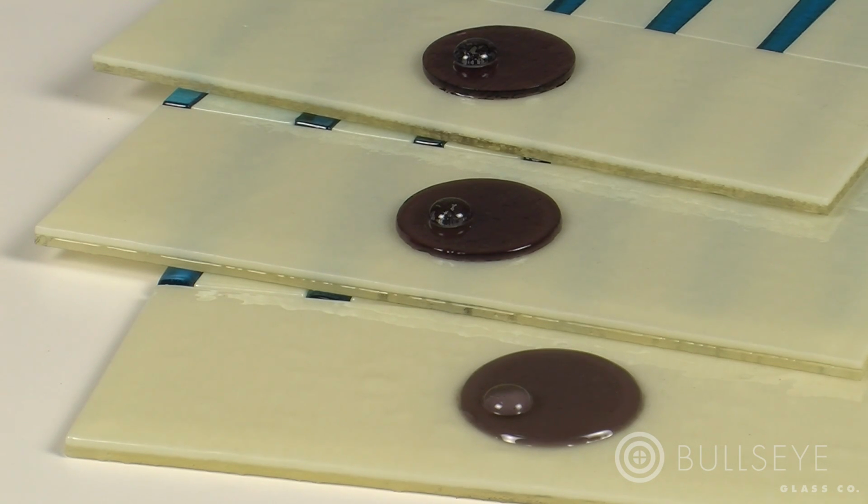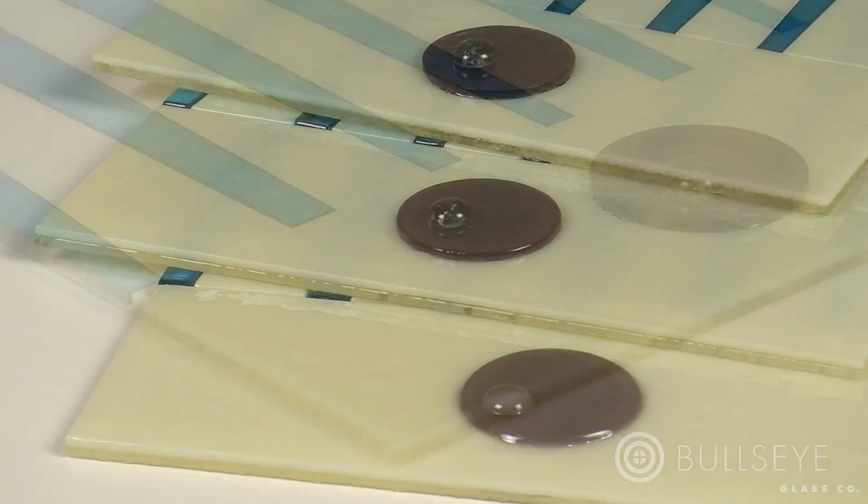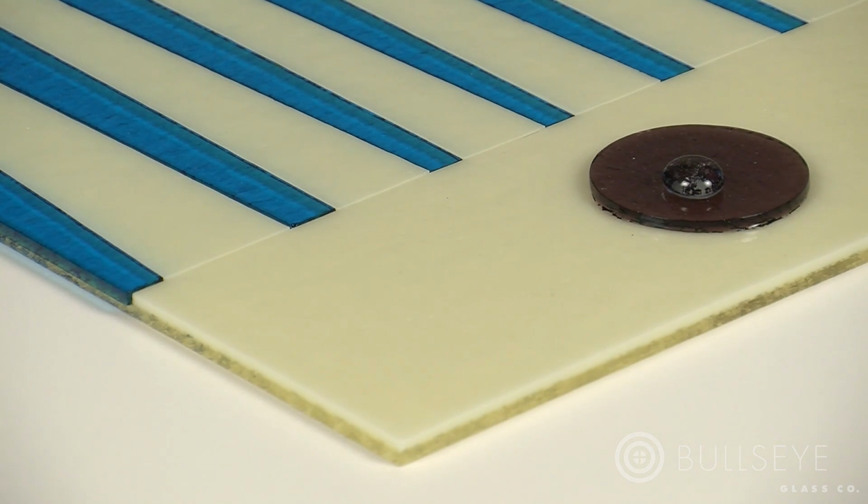After firing, the piece may have a wide range of qualities, depending on the top process temperature to which it was fired. On the lower end of the tack fuse range, pieces of glass simply stick together and retain all of their individual characteristics. This piece was fired to 1275 degrees and held for 10 minutes. Notice the considerable amount of texture still present.